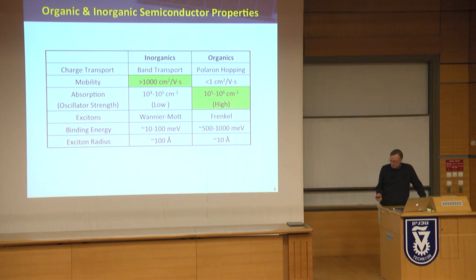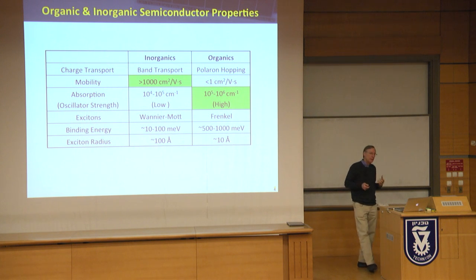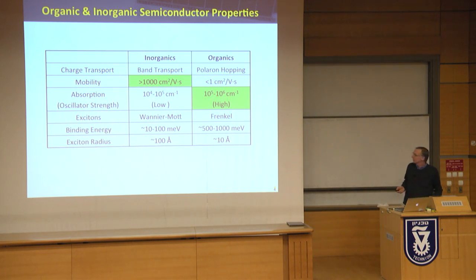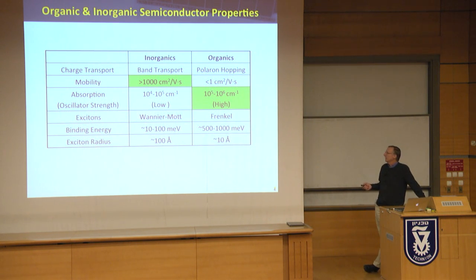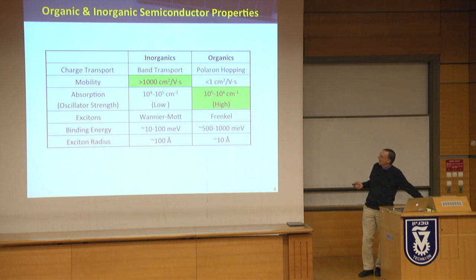Primarily, organic materials are known as excitonic materials. All of their optical properties really come from the fact that you create a molecular excited state, and it's very tightly bound because of the low dielectric constant. The low dielectric constant, of course, also results in a small exciton radius and a very large binding energy. In inorganic semiconductors, unless you make an engineered structure, excitons don't play a particularly significant role. It's mostly band-to-band excitations, but if you do happen to create an exciton just below the band gap, it's going to be a Wannier-Mott type of species. It's going to be quite large, extending over many lattice constants with a very low binding energy, typically unstable at room temperature.